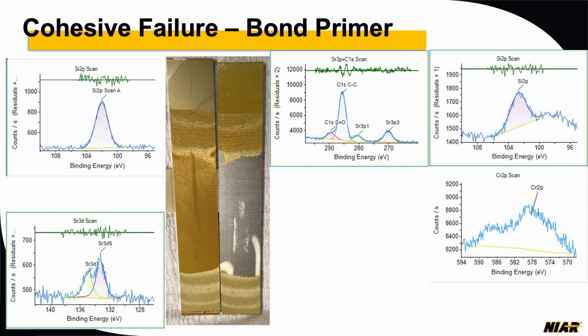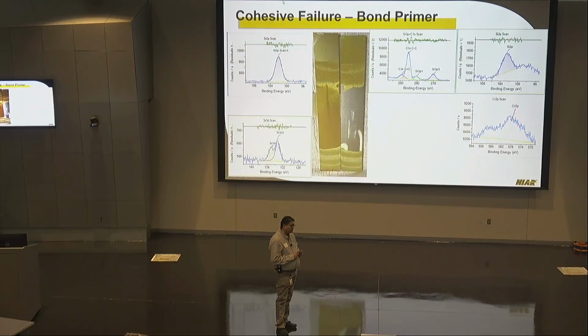On the metal side, we again detected strontium with pretty strong signals. There was a small presence of organic silicon again, and some part of the chrome signal was present as well. The signal to noise ratio was low because the chrome level was quite low. So, yeah. We are sure it's definitely organic silicon.